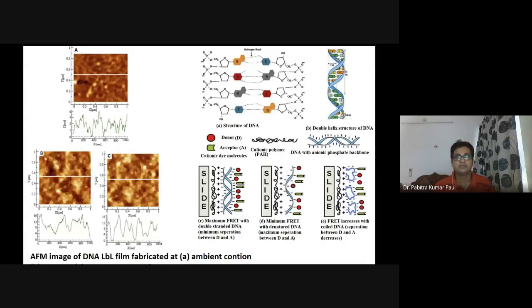And this is the atomic force microscopy. This is the normal ambient condition, the LBL film, and this is high temperature at pH 13 and temperature 95. And you see in this picture the separation, the maximum FRET, because they are very close to each other, and minimum FRET because of the maximum separation. And here FRET increases with coiled DNA, and the separation decreases compared to this one.